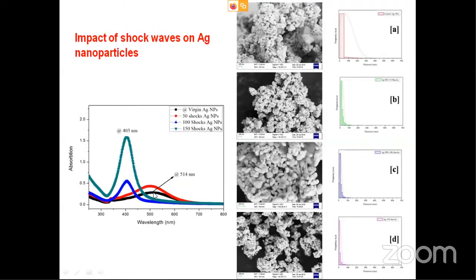But when you give 50 shocks, slowly this SPR peak is moving and the size is also changing. You can see the size distribution. Finally, after 150 shocks, the size of the nanoparticles is narrowed down, and you can see the SPR peak also. It is great evidence. So you can change the size of nanomaterials by exposing them to shock waves, and by changing the size, you can change the shape of the material.